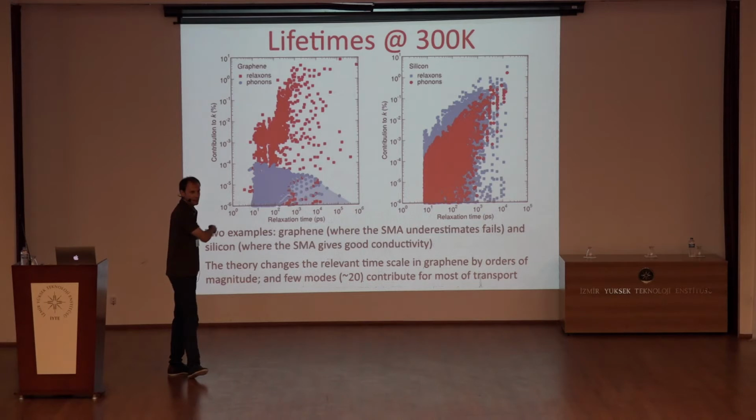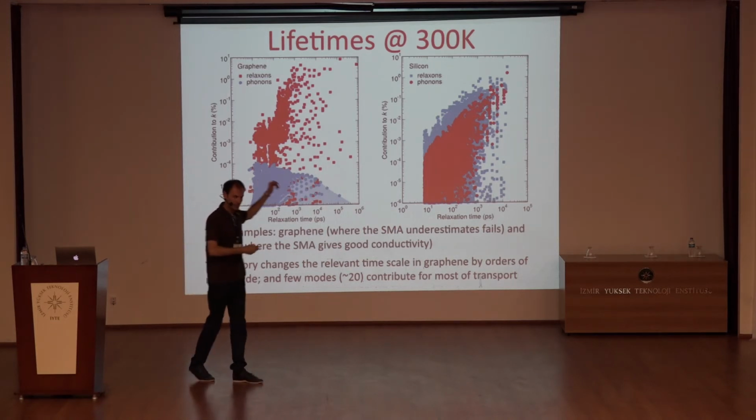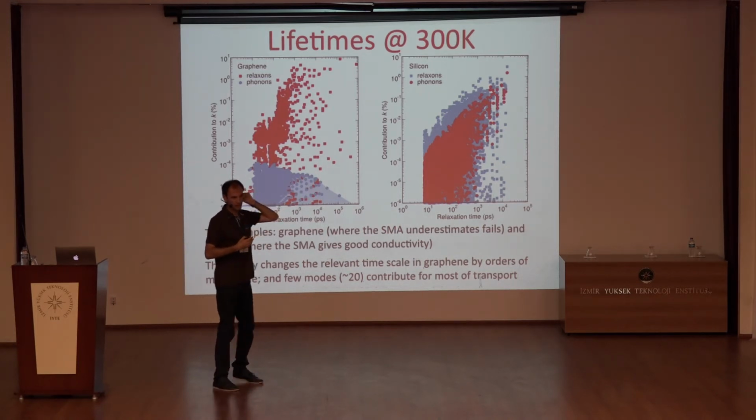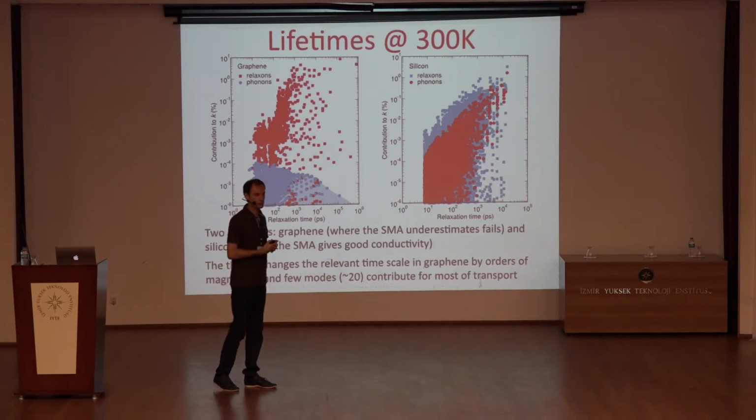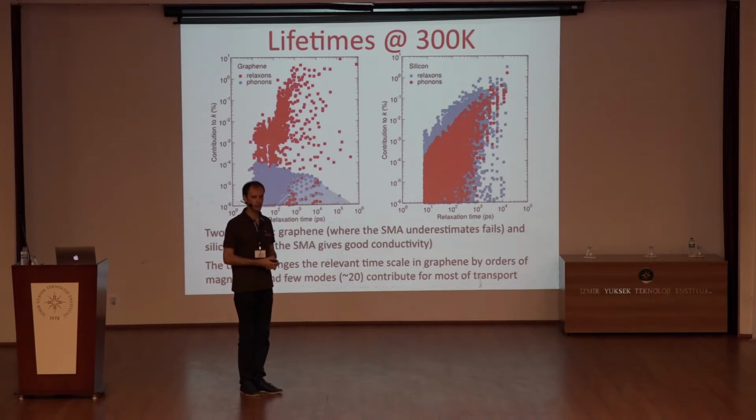Also, this is something that will have contributions from the diagonalization of normal, Umklapp, and isotopic scattering. But also here, since we are diagonalizing the scattering matrix, we are mixing much more the contribution from these different processes. That's also one way to say that if you solve the Boltzmann equation exactly, the Matthiessen rule does not hold. I'd like to explain a bit in more detail.